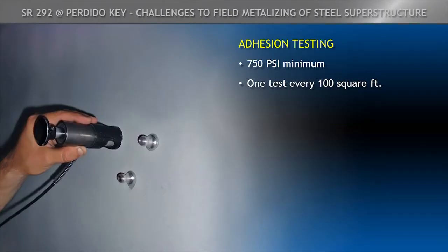The adhesion testing, we actually did one test per 100 square feet, and it had to be 750 PSI minimum. And with this particular standard, to get one test, you have to average 3 of these pulls. And you're going to see a picture in a little bit that these pulls actually cause a repair area if you pull the failure. And we'll show you how we handle that here in a little bit.